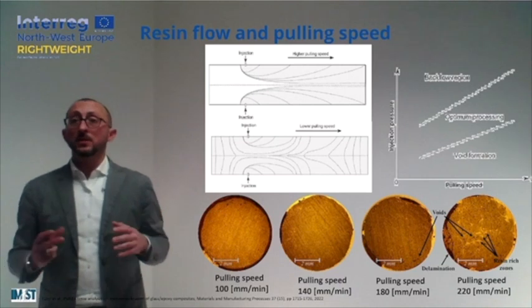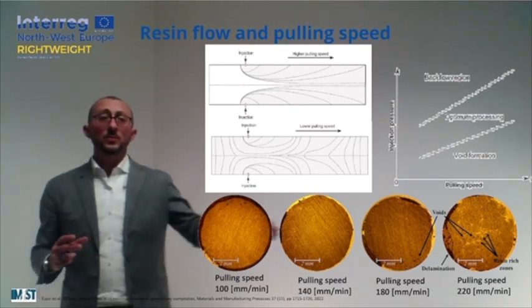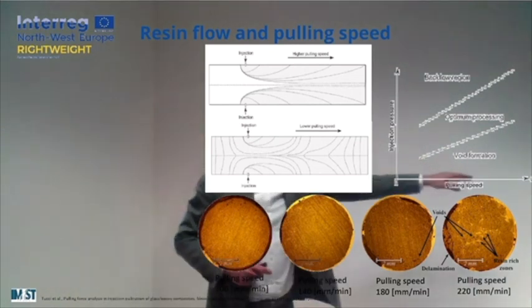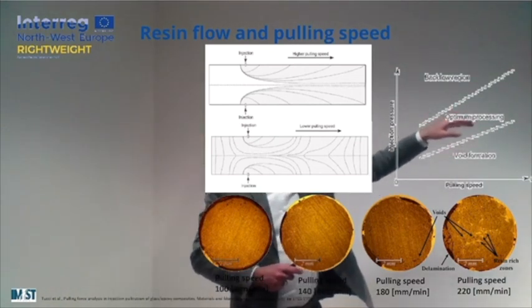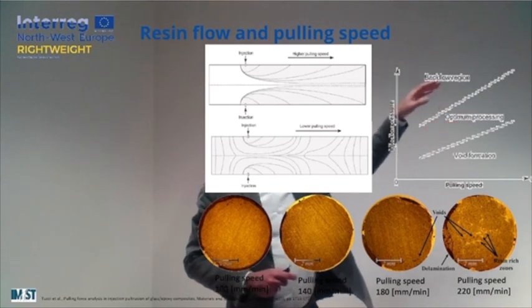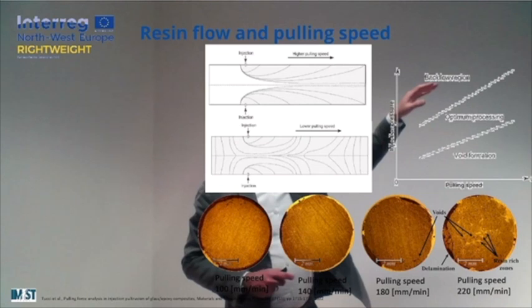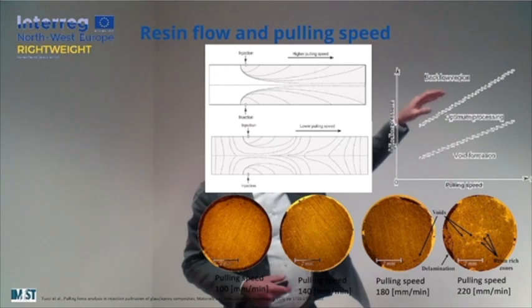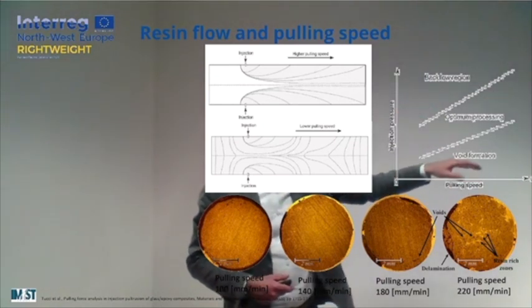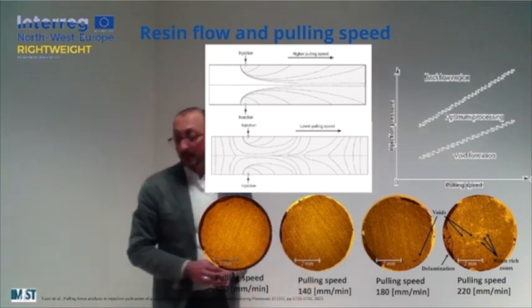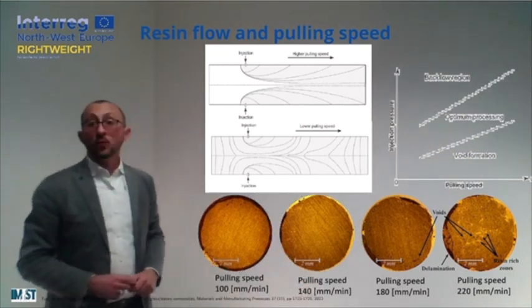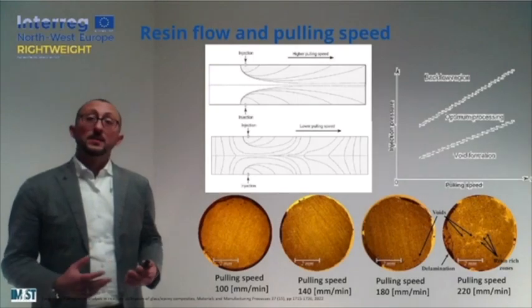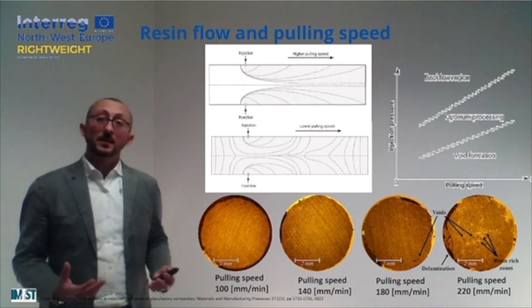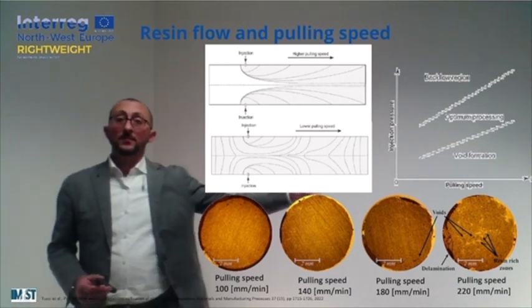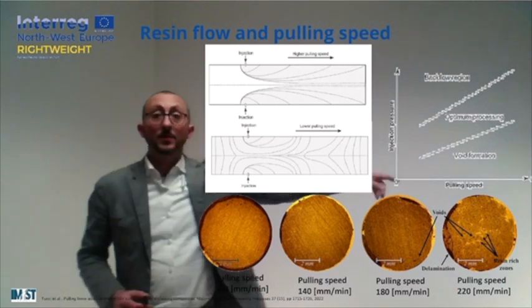If we want to imagine which is the suitable combination of parameters, actually we should stay in the middle of this graph here, in this optimum processing region, avoiding any kind of back flow when the pulling speed is not really suitable and we are working with a high pressure, or when we are pulling our material too fast and pumping our resin at low pressure. Increasing the pulling speed will be reason for other problems like internal defects and, once again, the production of scraps.